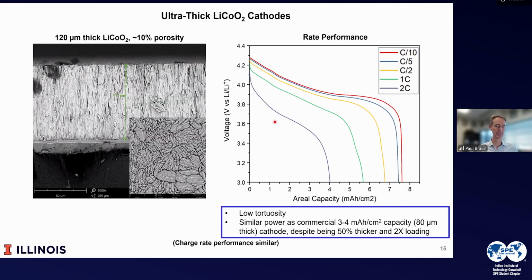So here are some examples of going thicker. Again, electrochemistry has the advantage. If you tried to cast an electrode this thick by slurry, it would crack as the solvent dries, or the tortuosity would impact performance. Here, this is now 120 microns thick. And so this has similar power as a commercial 3 to 4 milliamp hour per square centimeter cathode, even though it's 50% thicker and has 2 times the loading. So it has over 7 milliamp hour per square centimeter.